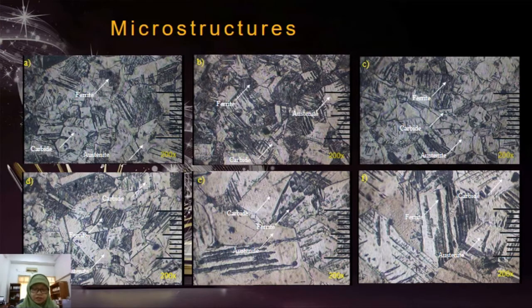After 5 minutes of immersion, the number of ferrite structures increases while the austenitic structures appear smaller. At 10 minutes of immersion, the visible phenomena are the loss of the ferrite grains and a dominant austenitic structure. At a longer immersion time, the austenite structure is increasingly visible with larger grains. It can be seen that the ferrite structure lamellas remain after 20 and 25 minutes of immersion. The carbide structure appears to be evenly distributed in small sizes. This phenomenon occurs in the raw material and after the cryogenic process for 15 minutes of immersion. At 20 and 25 minutes of immersion, carbides were seen to form lamellar patterns.